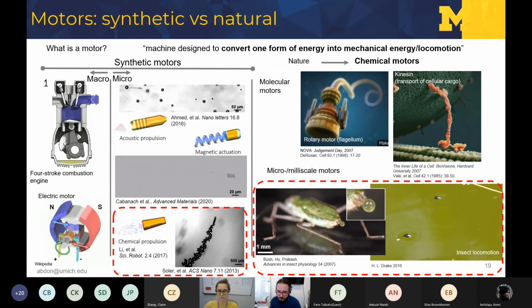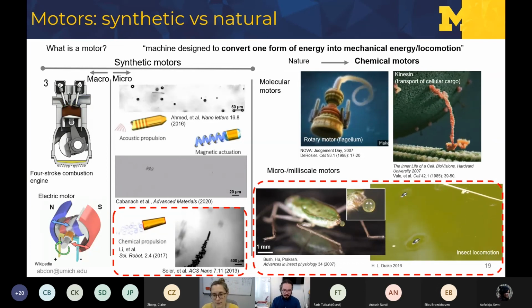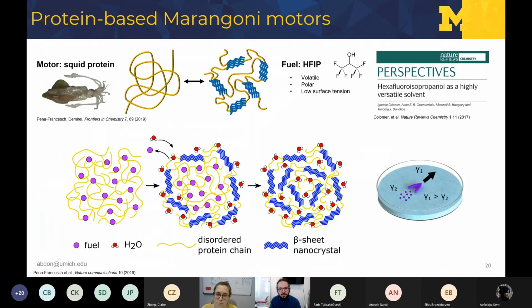So we wanted to take this concept and integrate it into our robots, right? And for this, we used the same protein material from the squids that we were talking about very recently. We used these proteins as the motor matrix, and we infused it with HFIP, hexafluoroisopropanol, as a fuel, right? This is a very volatile, low surface tension solvent. What happens is, it dissolves this protein, and also it blocks the formation of these beta sheet nanostructures.